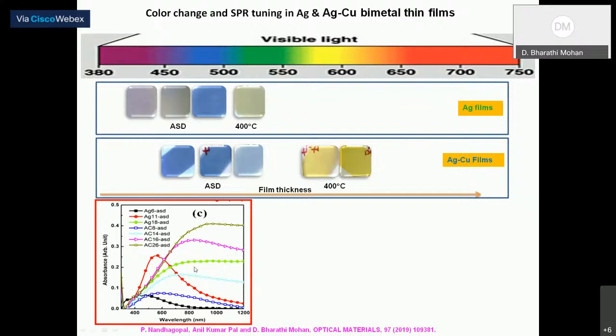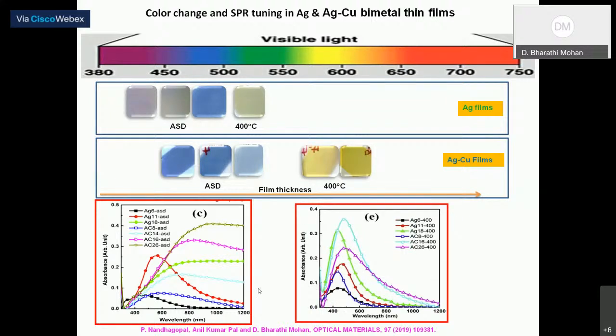And for the other films, you can see you have a long tail which is covering up to near IR region. If you anneal the same films at 400 degrees Celsius, you can get a very sharp SPR with a good homogeneity.